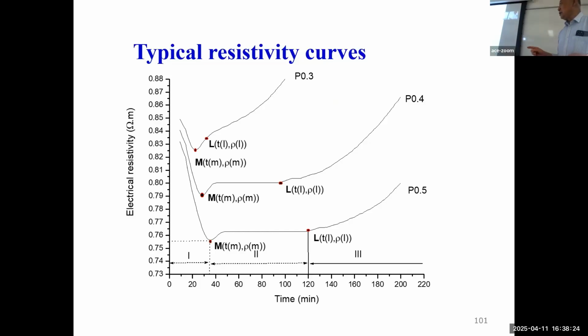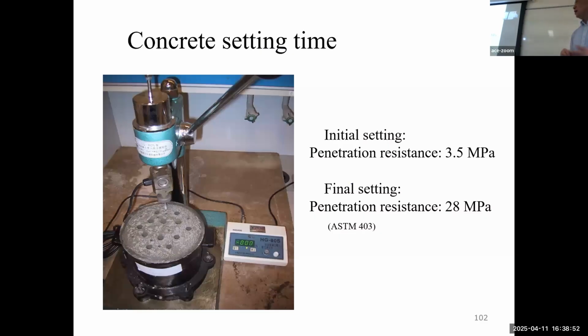My first PhD student used this to get his PhD degree. What he found is that this method is very reliable. For cement paste with 0.3, 0.4, 0.5 water-cement ratios, they have similar resistivity-time curves, and they all have this lowest point. Later on, we interpreted the lowest point as, in fact, the starting point of hydration.